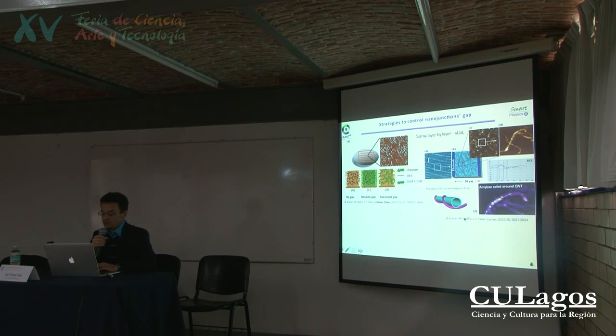And then if you assemble such objects, you will be able to control the distance between the objects by the coating with specific molecules. So in this case, the molecule is used to control the distance between the nano objects, and it's also used to detect organic gases. So there's a double use of the molecule. It's used for the selectivity of the sensor and also to control the junctions between the nanotubes.